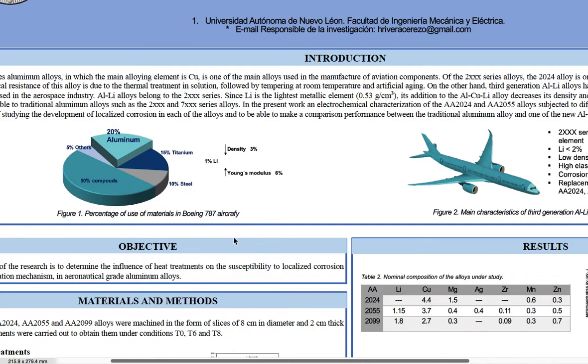On the other hand, aluminum lithium alloys belong to the 2000 series, with copper as the main alloying element, to which lithium has been added in an amount less than 1.8% with the purpose of reducing its density, since the density of lithium is very low, 0.54 grams per cubic centimeter. It has been observed that for every 1% of lithium added, the density of the alloy is reduced by 3%. In addition, the elastic modulus is increased by 6% for every 1% of lithium added.